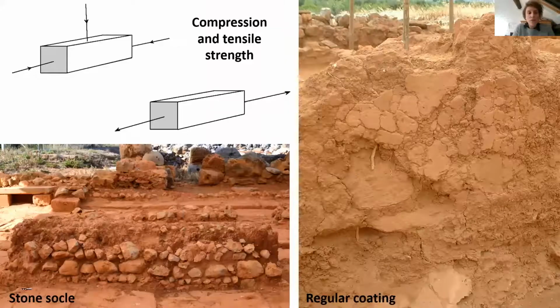Besides difficult conditions for their preservation, another reason why mudbricks are often absent from published reports and synthesis is that this building material is seen as structurally weak, with limited bearing capacity and low resistance to atmospheric conditions. But laboratory tests on the tension and compressive strength of sun-dried mudbricks have demonstrated their load-bearing capacity. And this load-bearing capacity can even be improved using a wooden framework set within the wall or by the incorporation within the mudbricks of fibrous material.